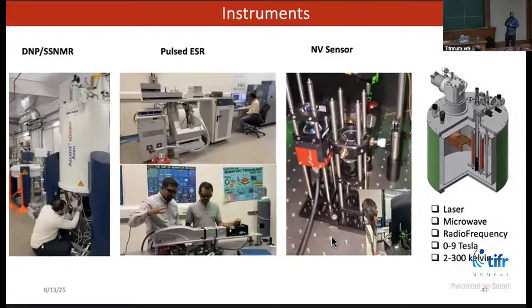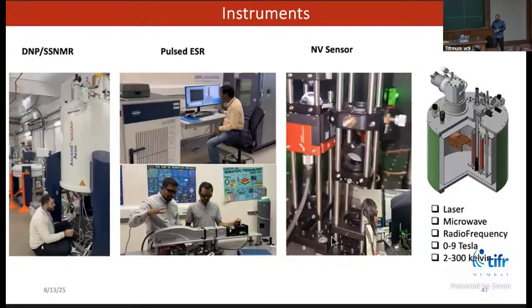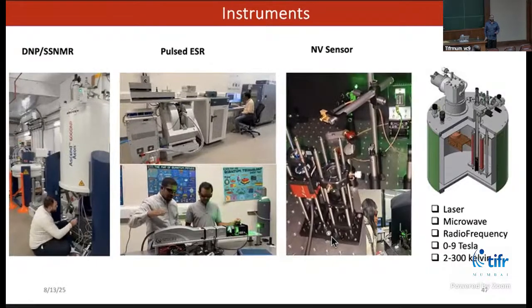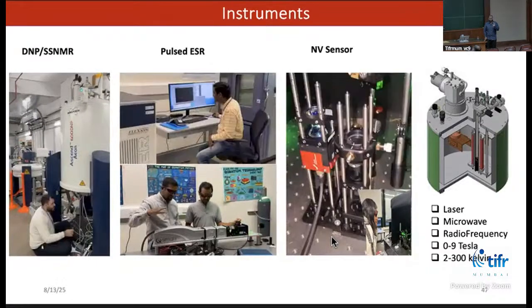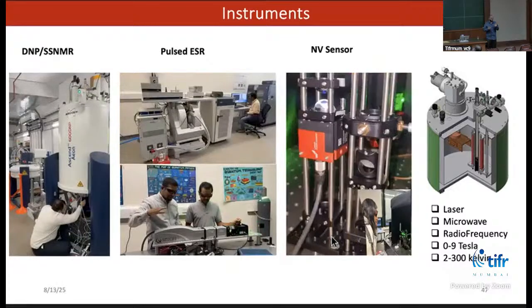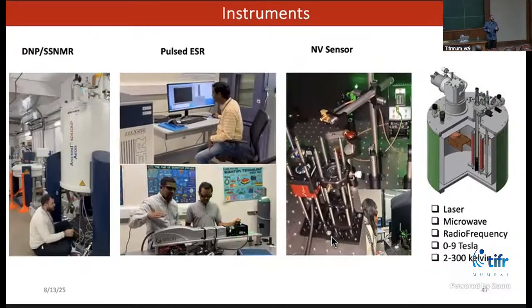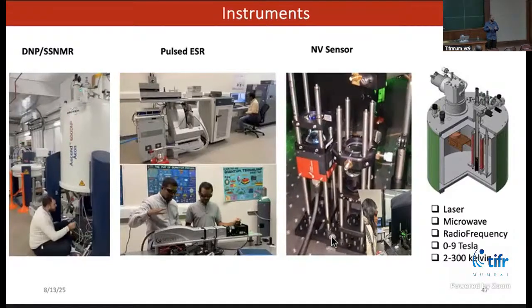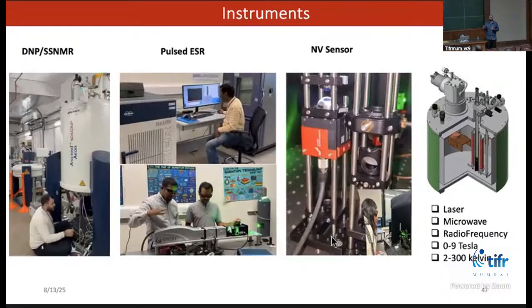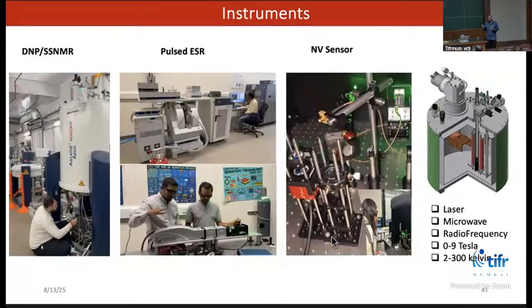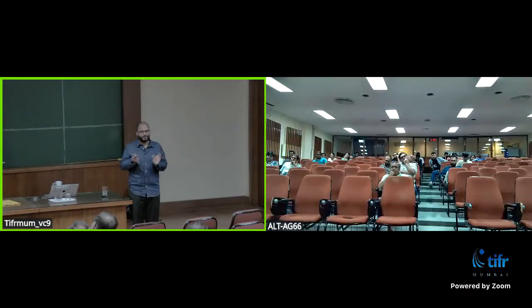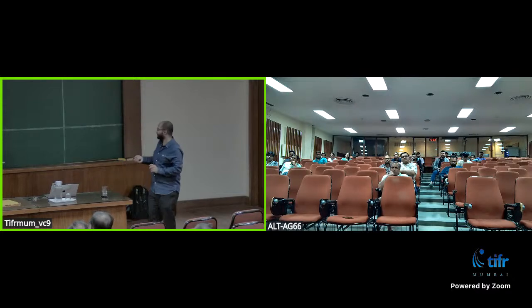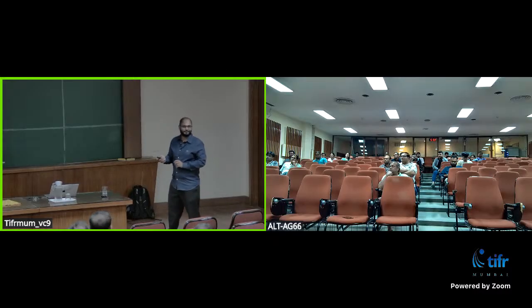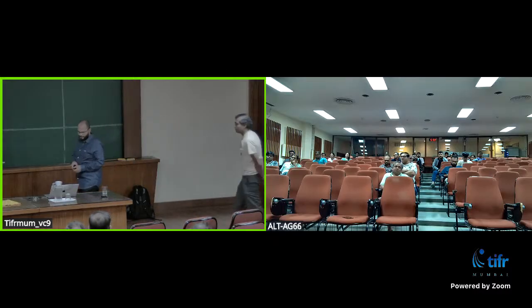And this is very much needed because most of the time, commercially, when people do DNP, the gyrotron, the source of microwave, is fixed. And that is fixed for nitroxide, so electron spins whose g tensor is close to 2. If you come up with another system whose g tensor is 1.8, commercially available setups would not be able to do DNP. But if we can sweep the magnetic field to be in resonance, then one can do DNP with any of the systems.